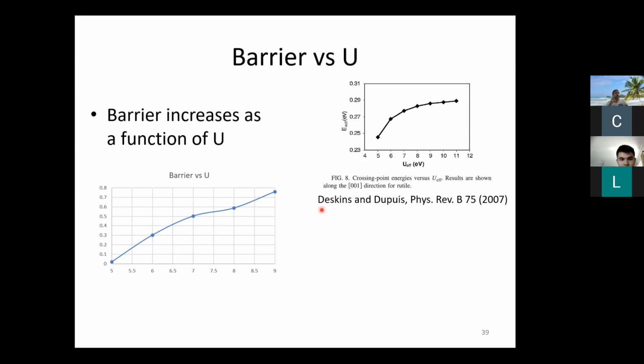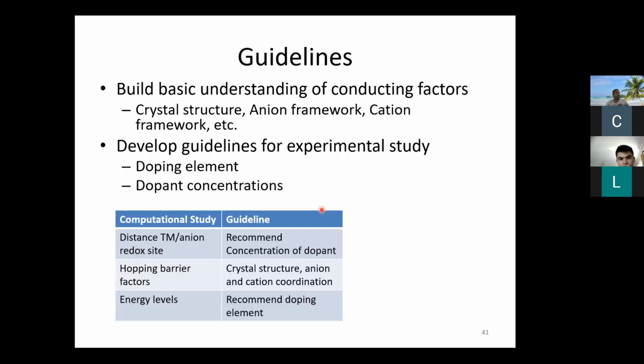I didn't go too much in depth into how this U parameter works, but it's basically adding a penalization of the Coulombic term on certain sites. In this case, you apply it to the d orbitals of the titanium. Once we figure out what kind of barriers we want to use, we want to tune certain things. We want to maybe distort some of these lattice structures, maybe change the anionic framework from oxygen to sulfur, maybe even some halides, and get a general picture of how the chemistry and structure affect these barriers. We may even dope certain elements on some of these sites and see how that is affected as well.